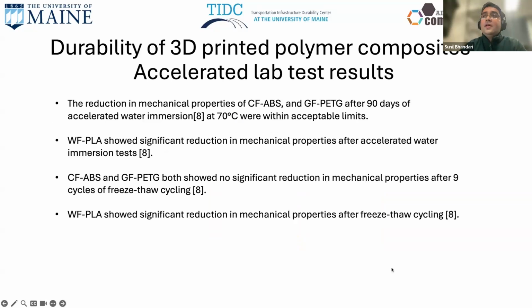So the results show that the reduction in mechanical properties of carbon fiber ABS and glass fiber PETG after 90 days of accelerated water immersion at 70 degrees C was within acceptable limits. There was very small loss. For WFPLA, there was significant reduction in mechanical properties, so it's not the best polymer system to use for parts that experience long-term exposure.